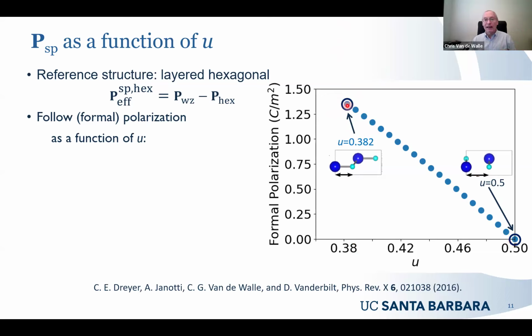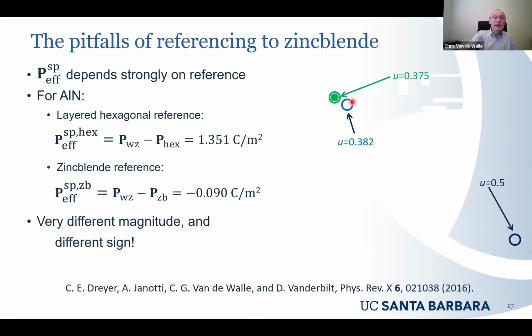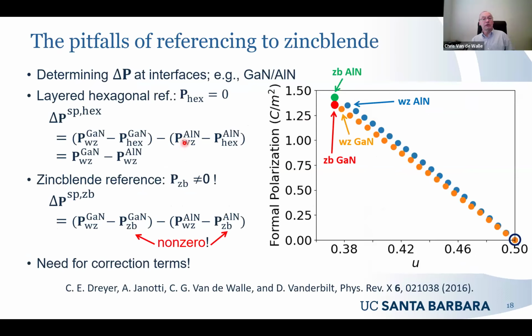And this is actually why we make these plots, not just for illustrative purposes, but to make sure that as we gradually change the structure from wurtzite to layered hexagonal, we stay on the same branch of the polarization. And since for layered hexagonal, we know macroscopically that this value gives us zero polarization, this assures us that this calculated value is the correct one to use for aluminum nitride. Thank you. Okay, so as I said, if we carefully keep track of what's chosen as the reference structure, there should not be a problem, even if you choose zinc blende.